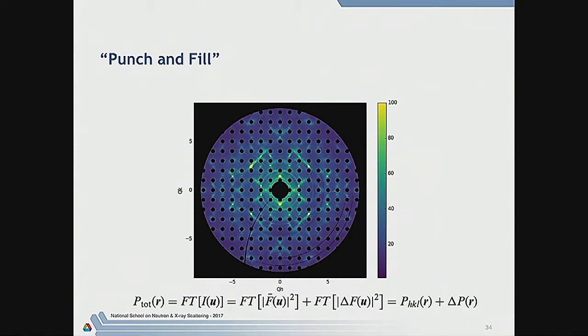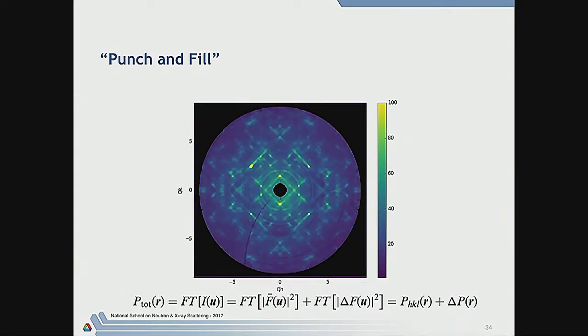So we take this three-dimensional data set, and we fill in little spheres around every Bragg peak. We've just put in not-a-numbers or something; we did this with just some simple Python scripts. But anyway, so that's the punch method. Now, of course, you don't just want to Fourier transform that. In principle, you could, but you'd like to fill the gaps, and so we actually used some astrophysics algorithms, which are used to find missing galaxies in their data or something. They have a way of interpolating across the intensities of their sky maps, which, you know, might be a bit suspect in some considerations. But anyway, it works really well here.